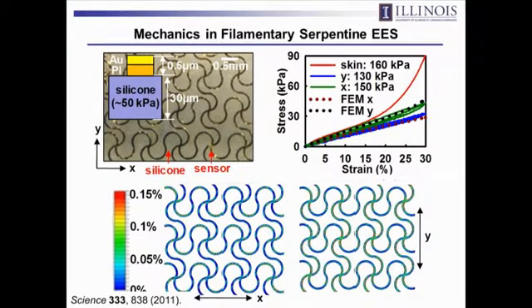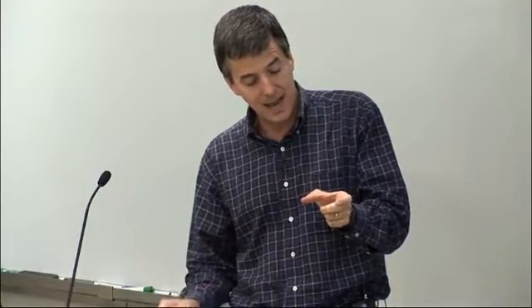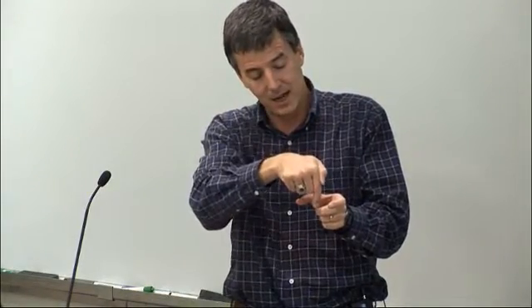So how do you get something that has very low modulus? I told you some tricks to get stretching, but now you need stretching, but also a very low effective stiffness. And it's a tricky problem. You want a device that has a modulus of, say, 100 kilopascals, but you want silicon in there, and that modulus is 150 gigapascals. So how do you do this kind of composite engineering? This is one way to do it.